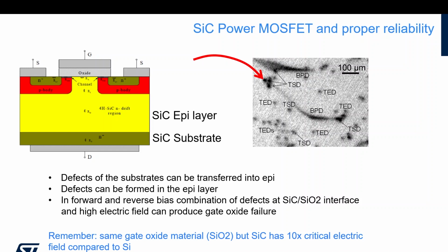The number that we transfer from the substrate to the EPI is fortunately reduced, but defects can still be formed. So in the gate oxide, in forward and reverse bias, you can have a combination of defects at the interface between silicon oxide and silicon carbide, and you can have high electric field. Because remember that we use silicon oxide again today. So you have the same gate oxide material, but due to the properties that I was showing you before, the maximum electric field that silicon carbide can withstand is 10 times higher than silicon. So while in silicon, at this interface, you can have something like 2 × 10⁵ volt per centimeter, now you can have 2 × 10⁶ volt per centimeter. So you have to be very careful about power.